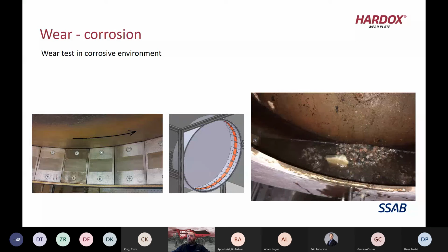And this one has some water and some chlorides added to it. That way you get more of a corrosive wear inside the drum, and so we can see what the actual wear rates are. After we tumble this drum for several days, we can take those samples out and weigh each sample, so we know what the wear or the mass loss is for each one, and correlate it to a wear life increase for each plate.